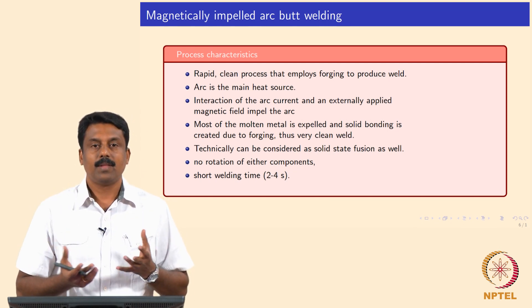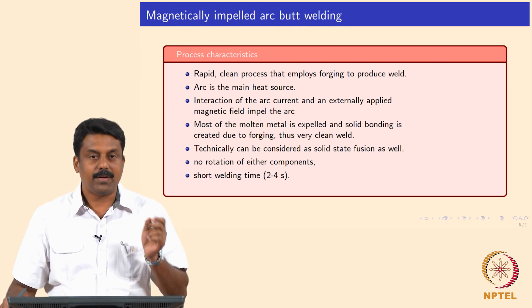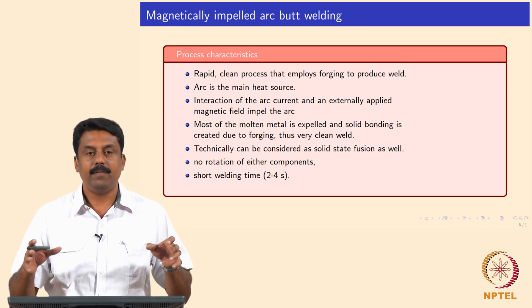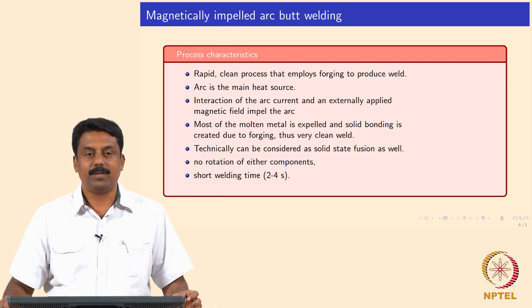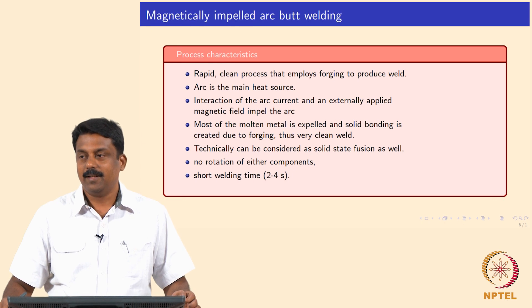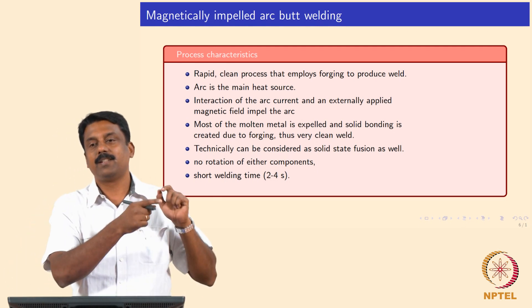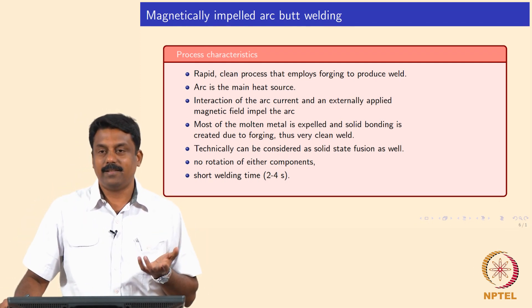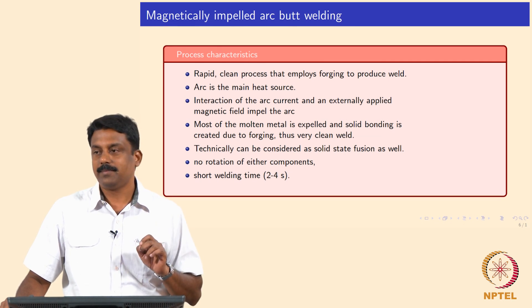The arc is the heat source - it melts the material and is impelled along the circumference and thickness to heat the material. Subsequently all the molten material is expelled by the upsetting and we have solid-state bonding of the interface. Technically it is a solid-state process, same as flash butt, but it still melts. We do not need to rotate the component - if you were using conventional GMAW you would have to weld in 5G configuration with the heat source going around the pipe, but that is not necessary here because the arc is made to rotate. Welding is achieved in very short time - 2 to 4 seconds.